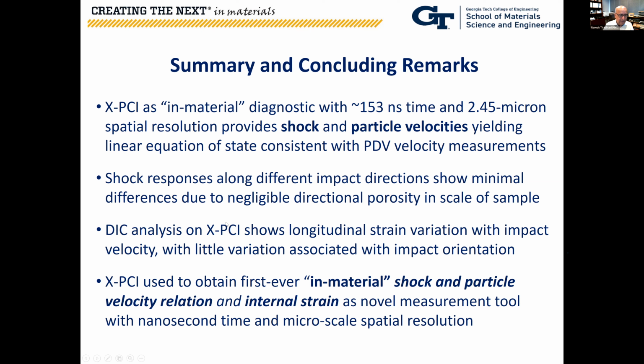Okay, the DIC analysis is a fairly reasonable method to be used here, even on the XPCI images, to monitor longitudinal strain variations. And again, there we see some difference, but not a whole lot. Okay, so finally, just to conclude that this is the first time that this XPCI technique has been used as an in-material measure of the shock and particle velocity, as well as the internal strain.